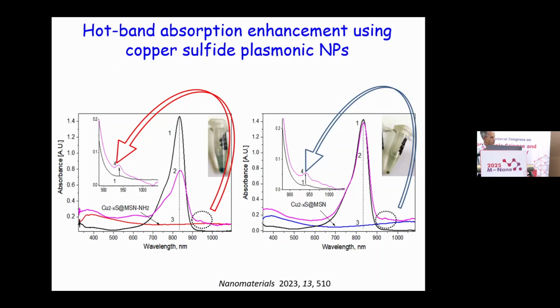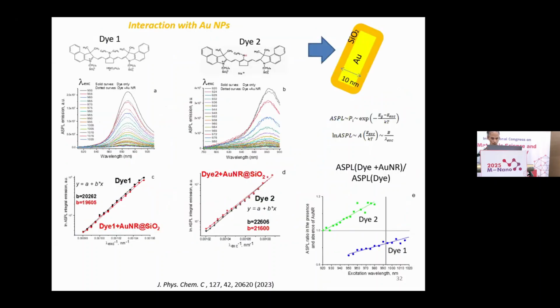So which just proves our concept that interaction with plasmonic nanoparticles can improve population of the hot band and therefore improve the intensity of the hot band absorption. Concerning enhancement of the anti-Stokes emission, the process is more complex, and we use two dyes in order to study enhancement of anti-Stokes emission.